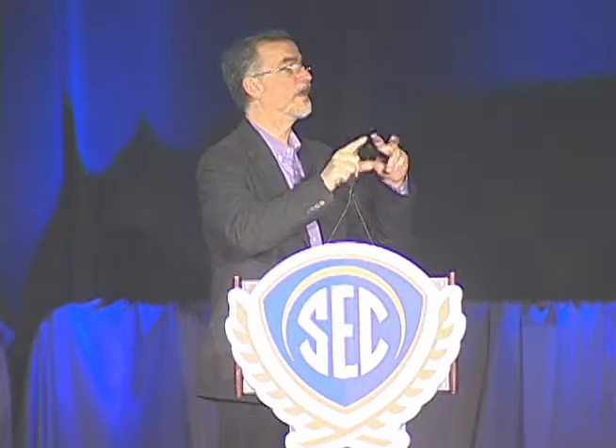We do a lot of grazing incidence X-ray scattering and experiments like that to confirm that what we have in the thin film is the same as the bulk crystal. These things really pack tightly. There really is only one way they can go together. In the two cases where we've seen polymorphs, they've both been where the trialkylsilyl group was unsymmetrical, so you'd have, say, two small groups and one big one, and one polymorph would have the big one pointing along the long axis of the molecule, and the other one would have it pointing along the short axis. So as long as the trialkylsilyl groups have been symmetrical, we really haven't found any polymorphs.